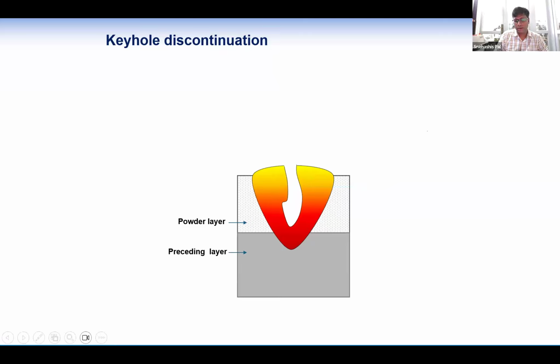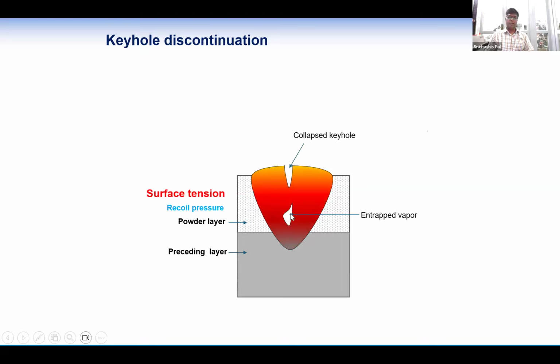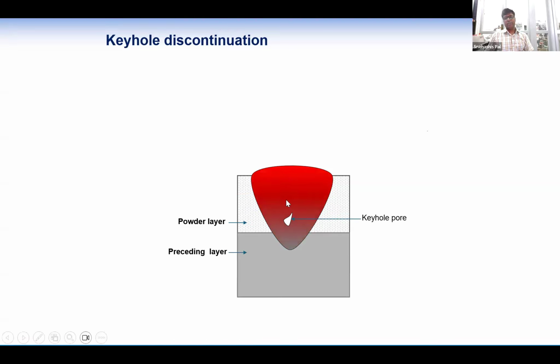Actually, it will grow into a bigger one, and when the laser falls down there, it will be deflected inside and make a gas pressure there from the evaporated material. Therefore, there will be a recoil pressure from the material vapor, and there will also be a surface tension from the liquid metal. If both are equal, then continuation will occur there. If not, if surface tension increases, then it can collapse, and there will be an interruption of vapor, and after cooling there will be a pore.